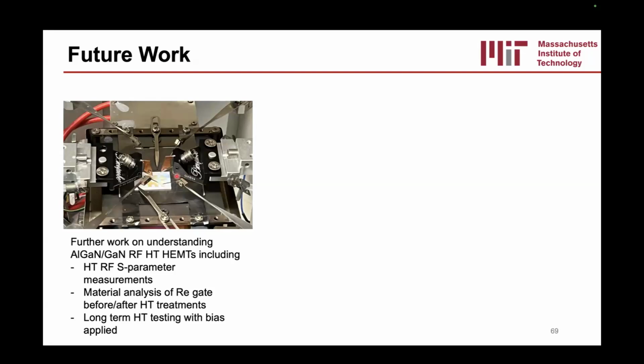Setup of the measurement, and so we didn't get a chance to do that here, but over the next few months, we hope to finish that. Additionally, we want to do a little bit more material analysis of the Re gate before and after the temperature sweeps. Understand, is it oxidizing? Is its stress changing? What is going on with it? And also ideally do some long-term high temperature testing with bias applied, which would be the most relevant use case. In our previous works, we didn't really apply any bias in the many hour long-term testing at high temperatures.